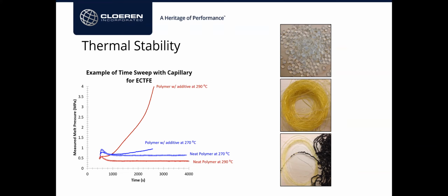That's fine. Is it relevant to measure capillary rheology on concentrates that are used at low letdown ratios, or should they always be compounded to understand the flow properties of the mixture? That's a good question. Definitely prefer to have a compounded material where the master batch is dispersed in the melt. That way will characterize the flow behavior. The flow behavior of a highly concentrated master batch can be so different that it will not make sense or be representative of the flow behavior of the compound.